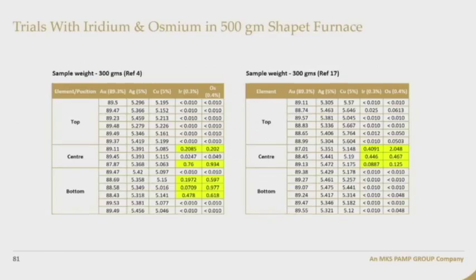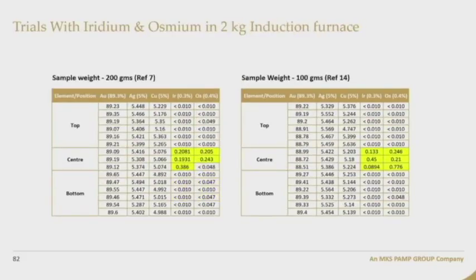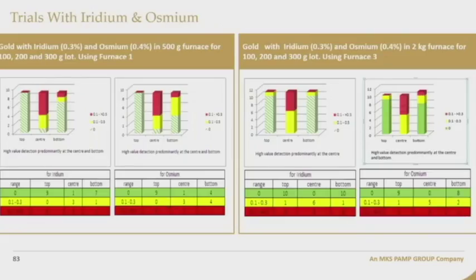When we added 0.3 to 0.4% of iridium and osmium in a gold alloy, we found more concentration at the center and bottom. In the second case, there was more concentration at the center. This was a typical case. We thought we would find more at the bottom, but in a number of results we found the presence more at the central cross section. You can see from the graph, wherever the red portion is there, it's always more at the center.